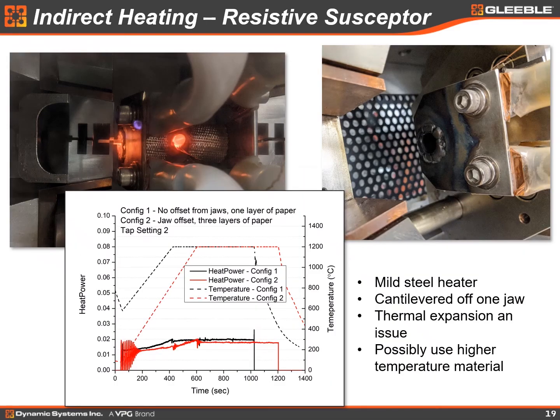Here are a few more pictures of the system, both during heating and afterwards, showing the red hot tube heating a ceramic specimen. We were able to get the temperatures up to 1200 Celsius, but having the tube coupled directly to one of the jaws made loading the sample rather difficult. Centering the thermal gradient was also a challenge, as the side that the tube was attached to was cooled much more than the free side. There were also problems with the tube itself bending and breaking at temperature, although the material designed for higher temperature service may be able to extend the capabilities and make this a more viable option.